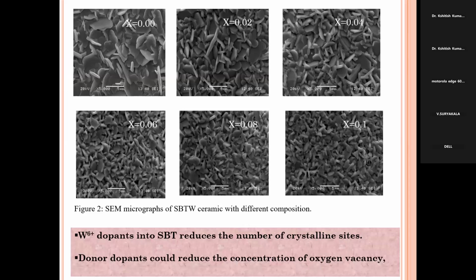This figure is the SEM figure, the scanning electron micrograph of the pellet samples. From that we also found that in the doped samples the grain size gradually decreases. The first one is for the SBT, but in the later ones the grain size is gradually decreasing. So we thought that maybe due to the smaller ionic radius of the tungsten compared to the titanium, the grain size gradually decreases.